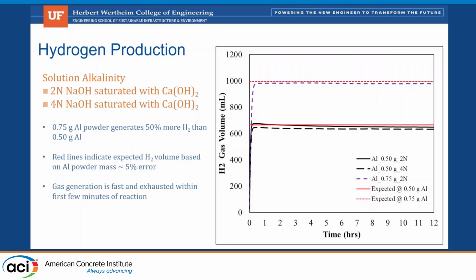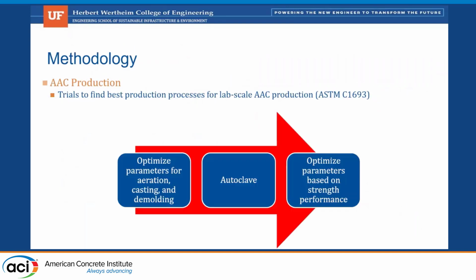We also realize that the gas generation has to be fast and exhausted within minutes of the reaction. That's really important because the particle size of our aluminum has to be small enough that we get reactivity and hydrogen gas formation while the concrete's still plastic. Otherwise, we don't have anything useful. So that's obviously going to be a driving factor of workability and so on.